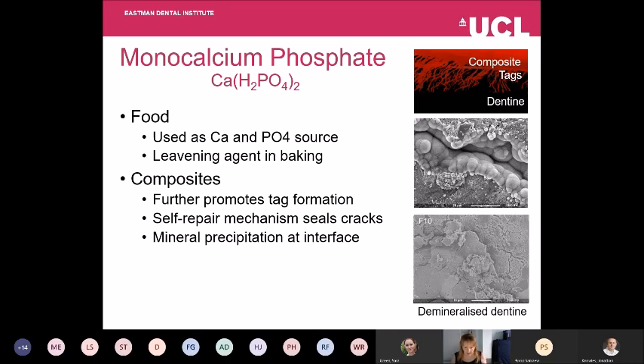The other component that we've added in that's from food is calcium phosphate. It's used as a source of calcium phosphate, which we need for bone growth, but it's also used in baking to make bread rise, as a leavening agent. In the composites, as we've shown, it helps to get this tag formation and sealing of the restoration interface. But we've also seen that if we take a composite and fracture it and then leave it in simulated body fluids, the cracks actually begin to fill with a calcium phosphate that seals up the fracture sites. So it helps us to get a self-sealing, self-repair mechanism.